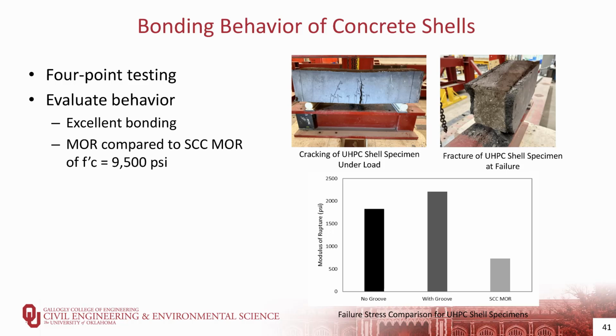Our previous student, Jake Choate, a couple of years ago, looked at casting both specimens simultaneously, as well as casting either the conventional concrete first or the UHPC first, and forming a mechanical texture on the interfacing surfaces. He found that the bifluid process, as he called it, of casting them at the same time actually gave the best result and was the easiest to do. Now for the UHPC shell specimens that are going to be pre-stressed, we're going to have to examine some different potential mechanisms between those two pieces to ensure that we get load transfer between the two. Unfortunately, we haven't gotten all that done yet.